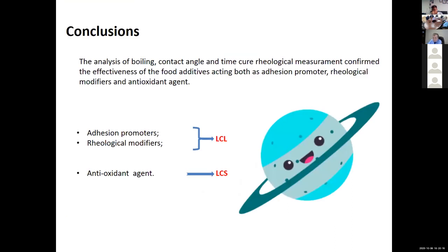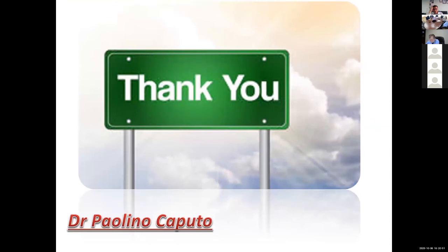In conclusion, the analysis of boiling test, contact angle, and rheological measurements confirmed the effectiveness of the food additives acting as adhesion promoters, as rheological modifiers, and as antioxidant agents. We can see the LCL additive is the best as adhesion promoter and modifier agent, while the LCS additive is better as antioxidant agent. Thank you for your attention.